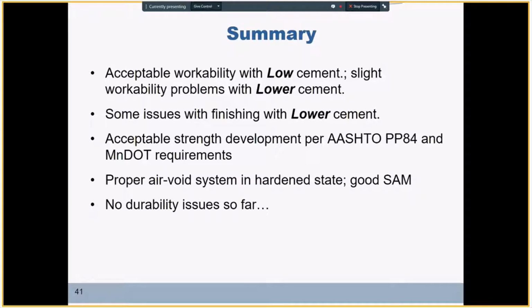Based on the laboratory data, sensor data, field test data, distress surveys, and field observations, I'd say we have had acceptable performance so far for both test cells with 470 and 500 pounds per cubic yard of cementitious material. There were some workability problems with lower cementitious content that need to be addressed for future projects, causing some finishing problems as we saw in the pictures. Other than that, we had no problems traceable to cementitious materials content - no abnormalities in strength development, no problems with heat of hydration, and no problems with maturity of the concrete mixtures.